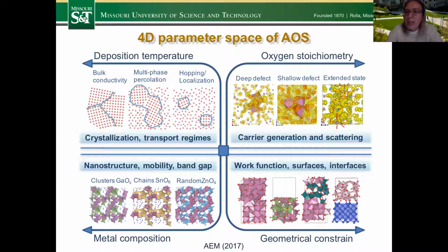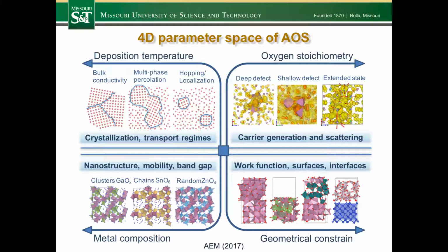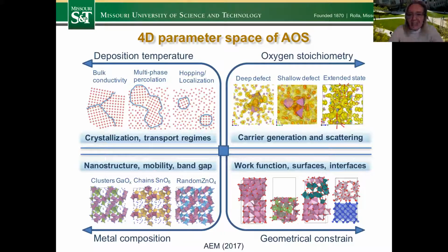Oxygen stoichiometry, obviously, I already mentioned that seemingly controls the carrier generation and scattering, but it's not, again, that simple. So we have to look separately at the oxygen stoichiometry, but then combine it with the previous parameters as well. And finally, I will briefly address the geometrical constraint. This is the work that we recently started on surfaces and interfaces and how geometries affect the structural and electronic properties in these fascinating materials. So let me start from the deposition temperature.